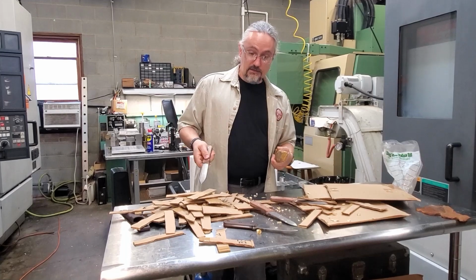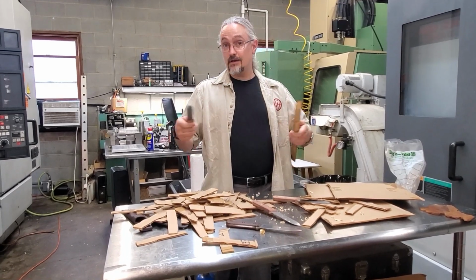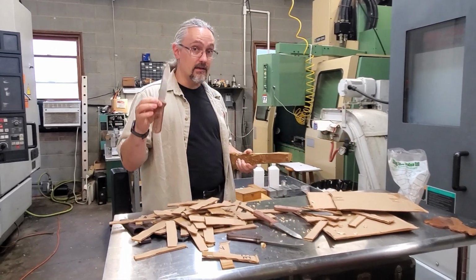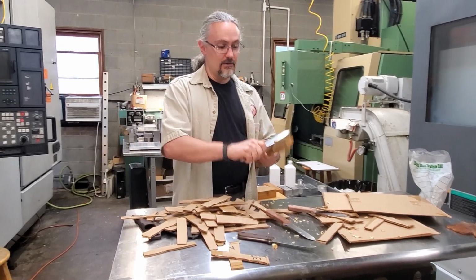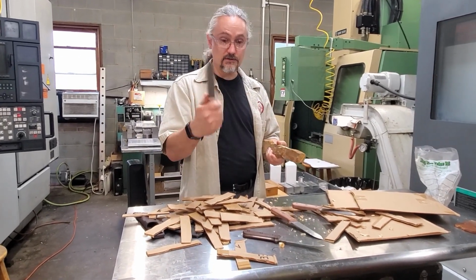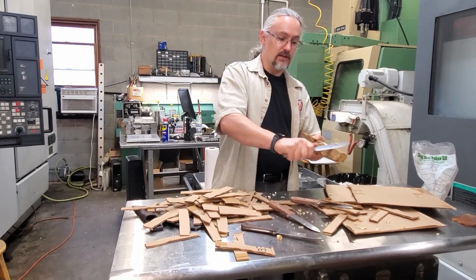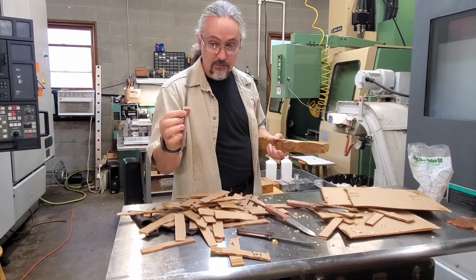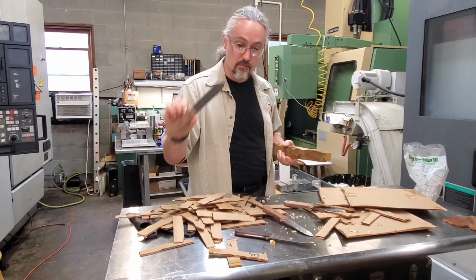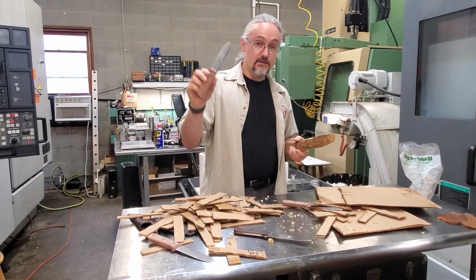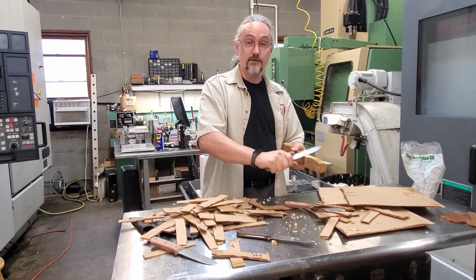It didn't do fantastic in the cardboard, but a lot of people don't cut a lot of cardboard. A lot of people go camping and there's not a lot of cardboard in the woods. They're doing things that put stress on the edge, and the edge stability of AEBL is actually quite good. So I would expect this AEBL to stay sharp better than this CPM 3V in this kind of use.